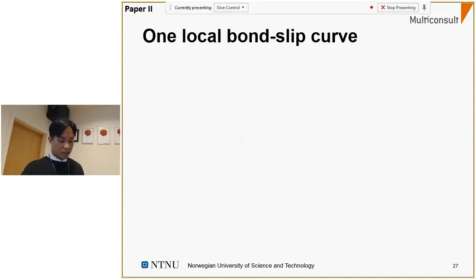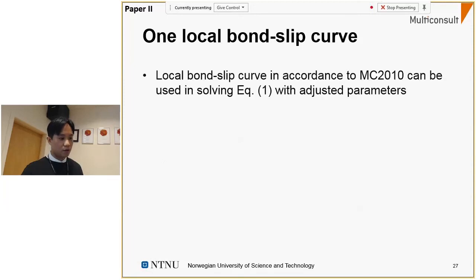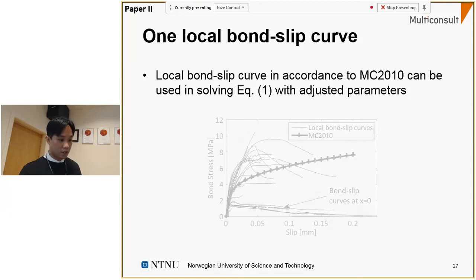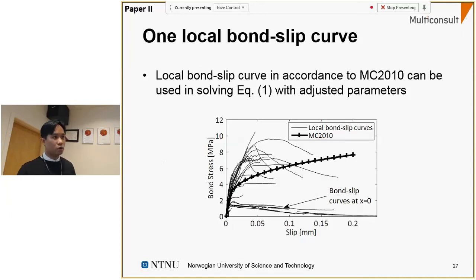And finally, one of the most important findings in this paper is that we only need one local bond slip curve, which can be used in accordance to MC2010, that can be used in solving differential equation 1, however, with adjusted parameters. So here we have the different local bond slip curves for all of the investigated specimens at different locations over the bar length. And we see here that we can use one local bond slip curve for the average response of all of these RC ties.